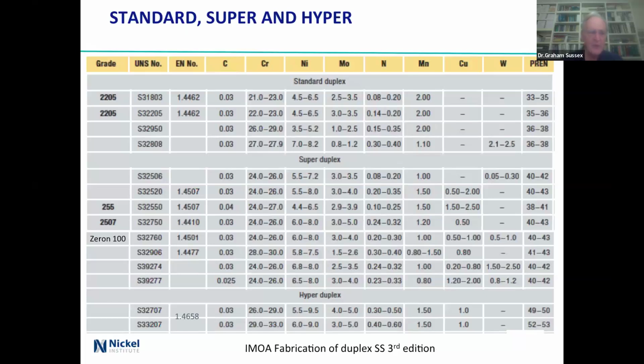The standard ones, 2205 is the one that everybody knows. One thing that perhaps people should realise is that the old 31803 is dual certified with 2205, and there's the compositions, and you can see why. Basically, the 2205 takes the top half of the corrosion resistance, the chromium, the moly, and the nitrogen, and you've got that sort of level of 35, 36 corrosion resistance PRE.